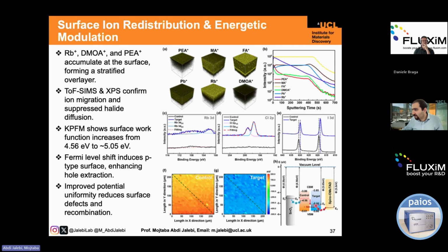So basically, we have better charge collection from the perovskite to the contact. That's the meaning of better band alignment. And also a more homogeneous surface potential within the film means improved uniformity within the film, as well as reducing the surface defects and recombination.